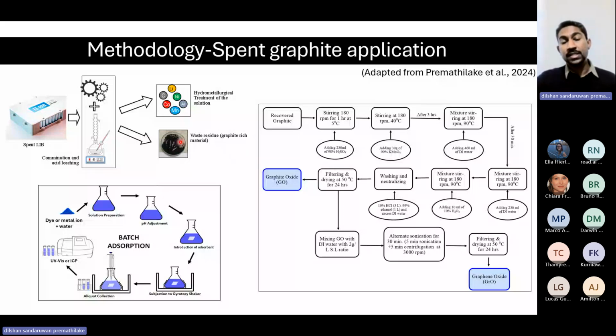I didn't use it as it is because the graphite still contains some amount of trace elements like manganese, cobalt, and nickel. Because of this, I have to modify this waste graphite to make graphite oxide and graphene oxide, because both of them have very high adsorption capacities, really higher than the graphite. This is the main reason why I converted it into graphite oxide and graphene oxide.